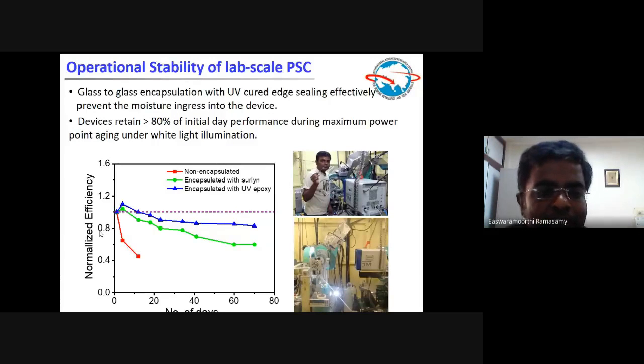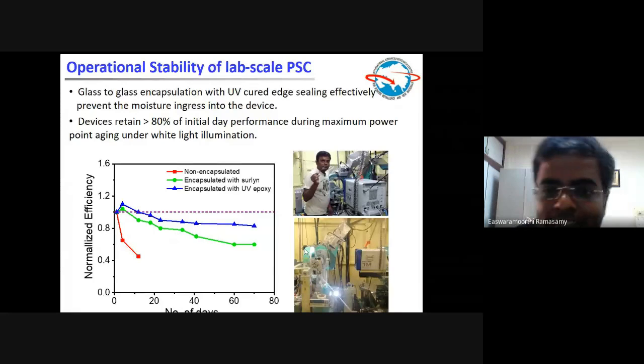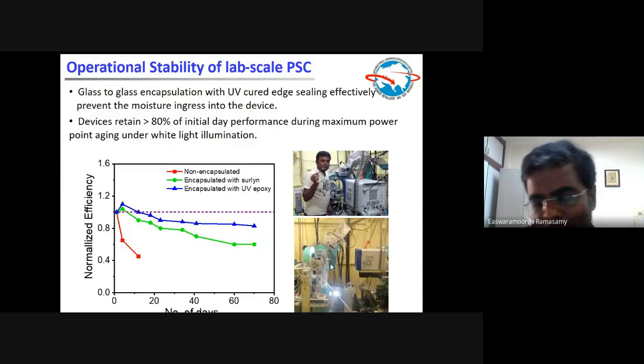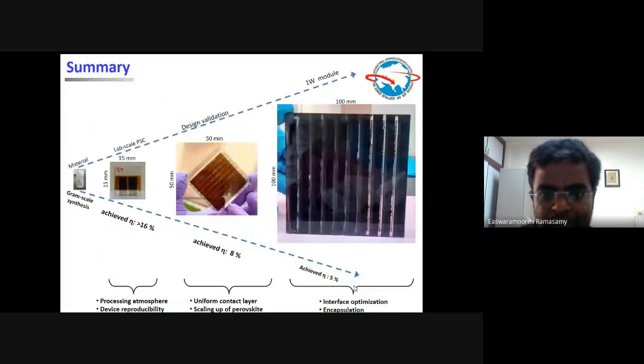So these are all the outcomes at the efficiency level, but a lot of optimization, internal analysis, and then molecular level degradation studies happened, and we used synchrotron X-rays and in situ XRD and other techniques. These are two pictures of where we utilized the high energy X-ray beam, at the Photon Factory in Japan and the Stanford Synchrotron Radiation Laboratory in the USA, for understanding the degradation of these perovskites.